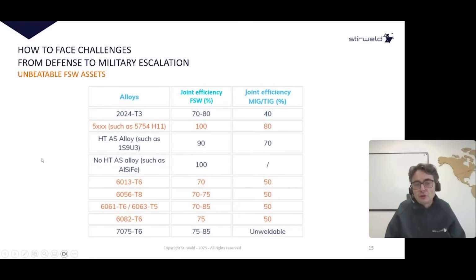Now when we look at the joint efficiency, here is a clear example comparing friction stir welding and MIG TIG. For example, on 2024 T3, we can reach 80% joint efficiency using FSW, while we reach 40% using arc welding. Why is that possible? Again, solid state. When we weld using friction stir welding, we use a lower